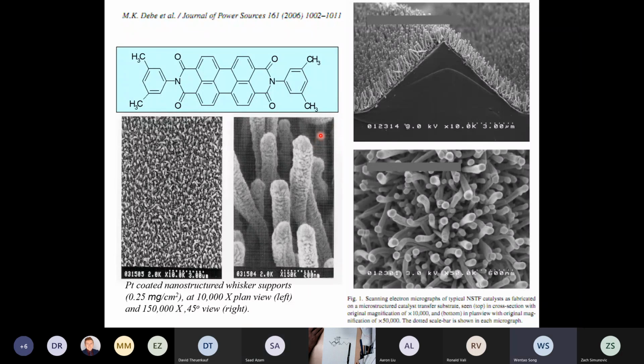Jeff, just also a follow-up comment on that. It's unconventional that the sputtered platinum atoms won't damage these organic molecules, because normally, my experience is that organic molecules are very susceptible to ion bombardment. It looks like for these specific molecules, 3M found they're very stable during the platinum sputtering process.